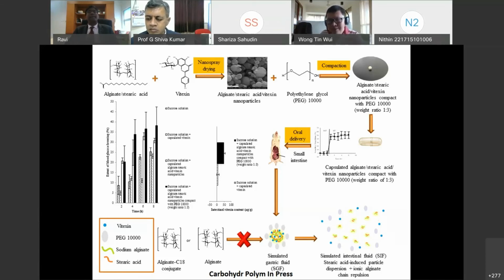Now, in the intestinal regions, what happens exactly is that the PEG will be eroded with time in the intestinal fluid. And very importantly, the nanoparticles are constituted of alginate and stearic acid. Now, alginate is a polyanionic polymer. So in the intestinal fluid, it will experience ionization, losing its proton. It will carry a negative charge and the alginate will repel each other